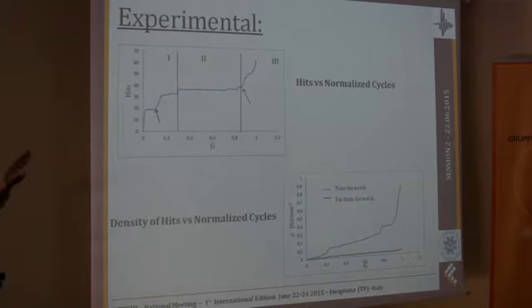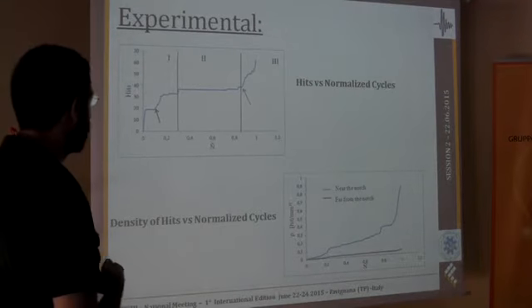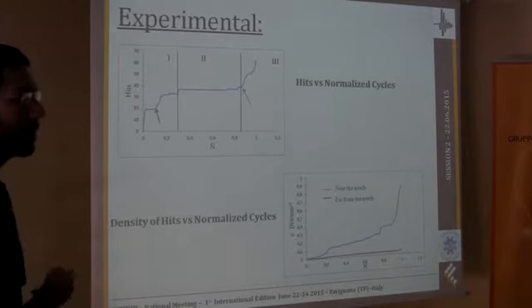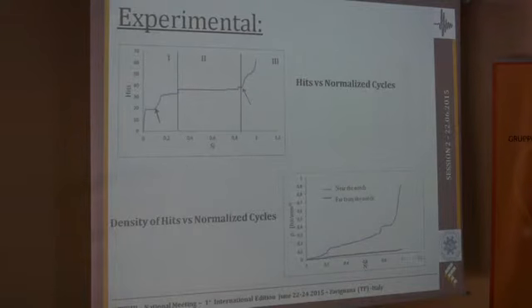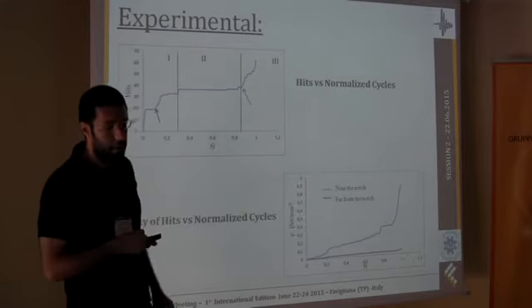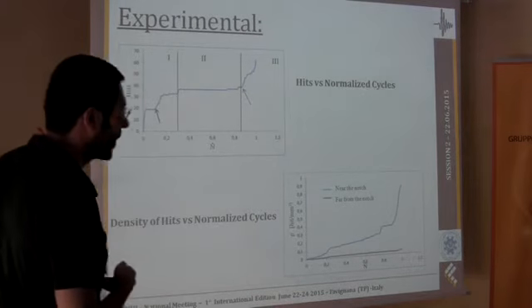These three stages in the features of the evolution of the number of hits in the test can be reconnected to the three stages of damage evolution inside the sample. Here we have phenomena which are connected to crack initiation. Here we have the stage of stable crack propagation. And the third stage can be connected to the stage of unstable crack propagation.